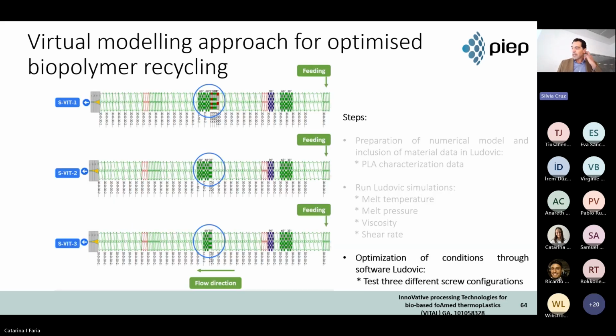So the next step was working on the screw configuration, keeping the processing parameters optimized, and then running the screw configurations. We start with the configuration on the top, and I would say it is a standard configuration for fossil-based materials. We wanted to start with this configuration and then try to identify what was the best approach. So with the results, the approach was to soften or lighten the aggressivity of the mixing elements on the screw. So we focus on the elements in the middle of the screw, and the two variations of the screw configuration were lighter than the first one.